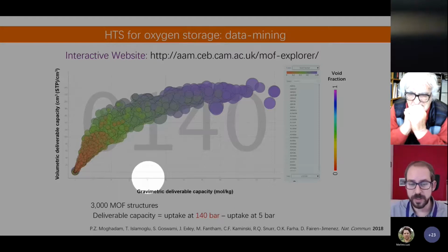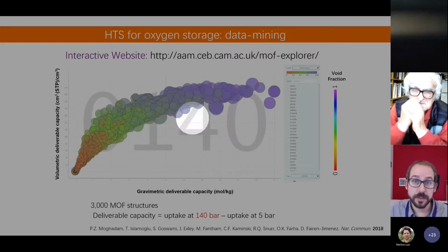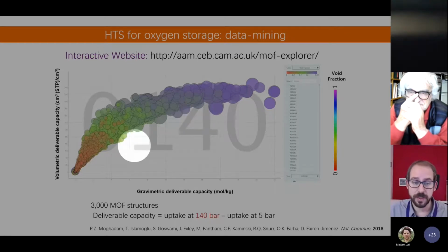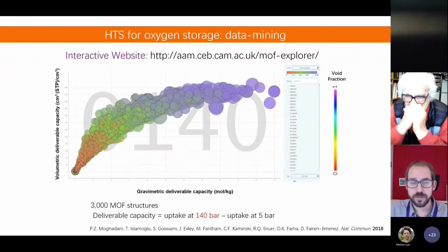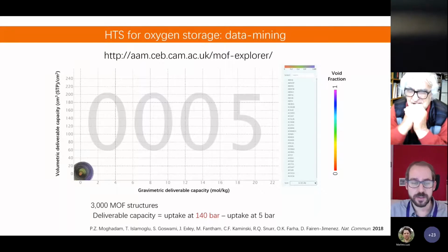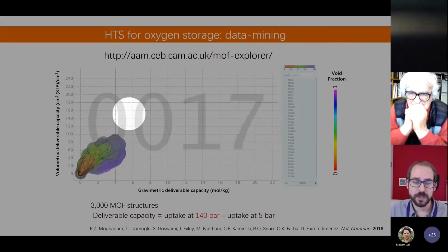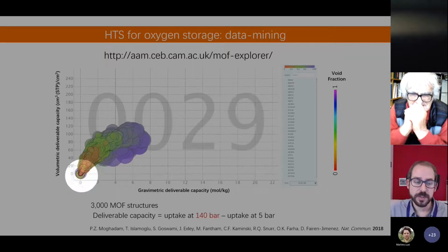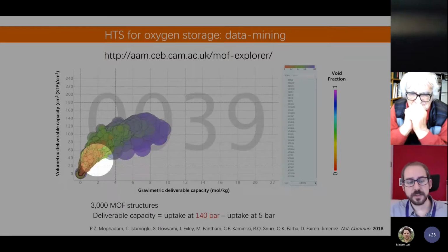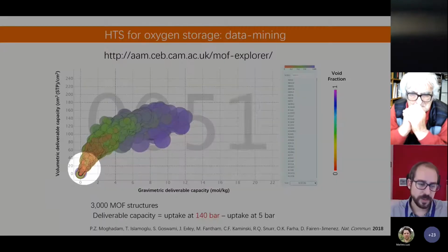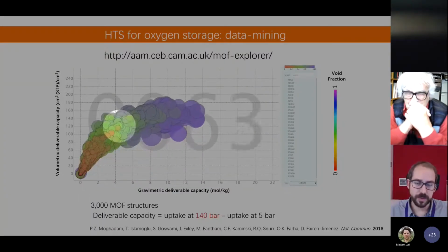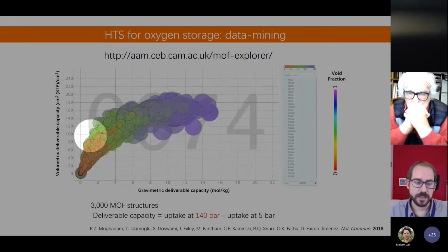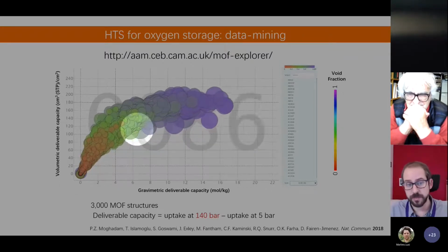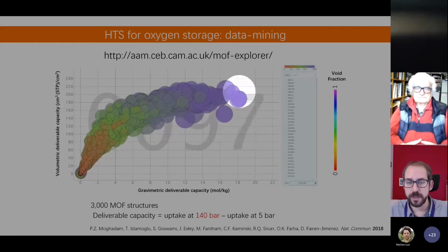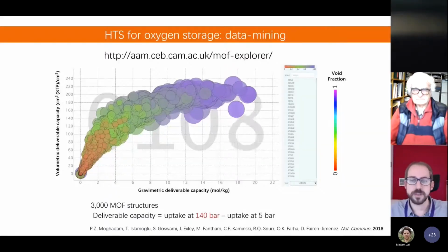On the other axis, you have the gravimetric capacity. This number in gray is the pressure that we are using for storing the oxygen. And every single sphere here is one metal-organic framework. This is the dynamic representation of all these different simulations. We increase the pressure, and you can see how the different materials start evolving in this process. You can see how the materials with lower void fractions and smaller sizes get stuck at lower uptakes. This is something you can imagine. Whereas all these purple materials continue growing when we increase the pressure.